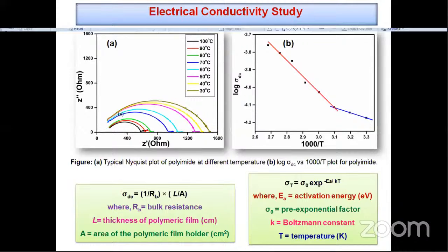Now, electrical conductivity study. The electrical conductivity of the synthesized polyimide can be studied with the help of an impedance analyzer. This is the Nyquist plot of the polyimide at different temperatures. Here, the value of Rb can be determined from the semicircle on the real axis of the Nyquist plot, and the dc conductivity can be calculated using this relation, that is, 1 by Rb into L by A. Rb is the bulk resistance, L is the thickness of the polymeric film, and A is the area of the sample holder.